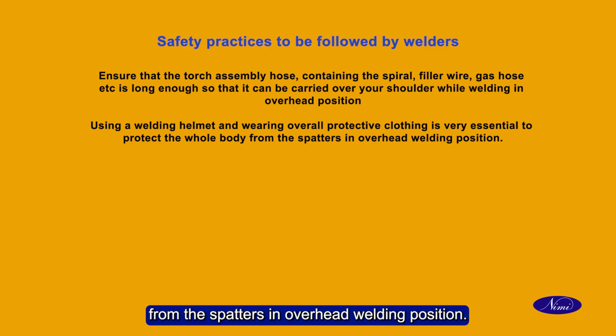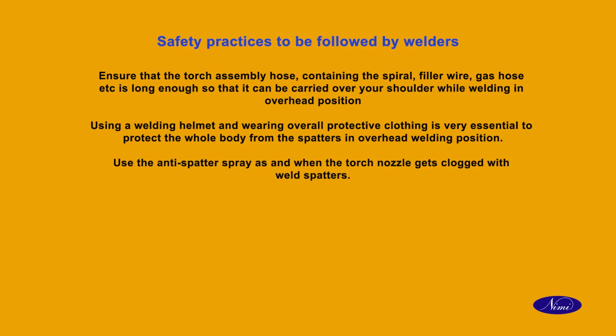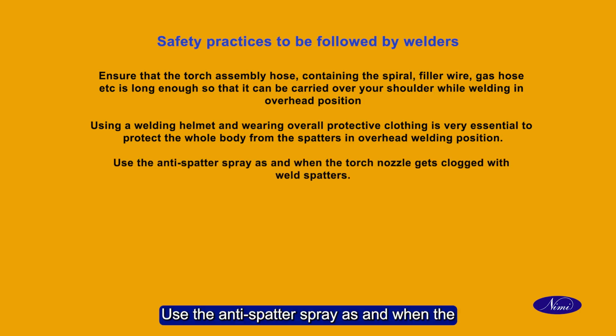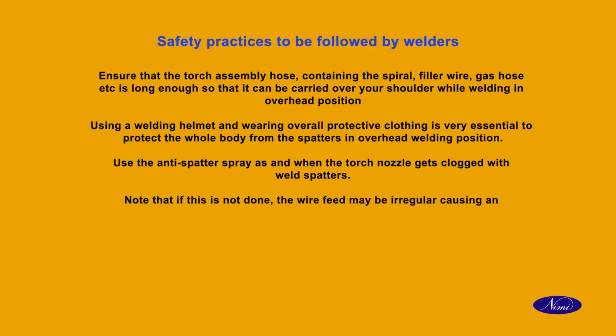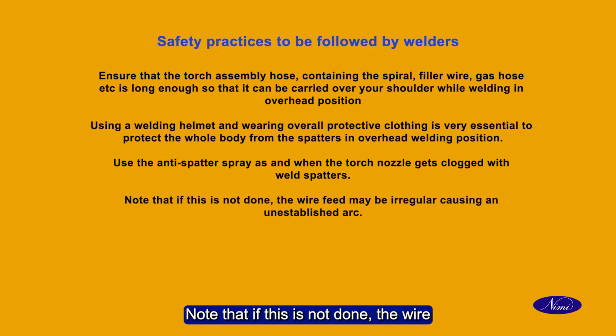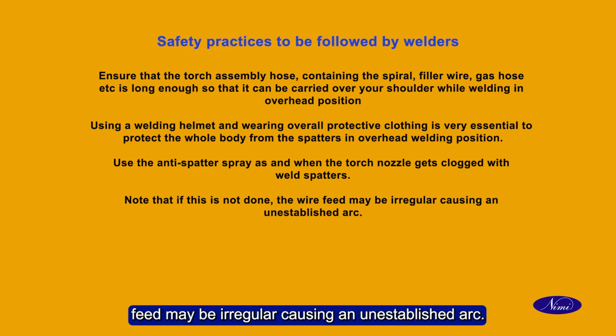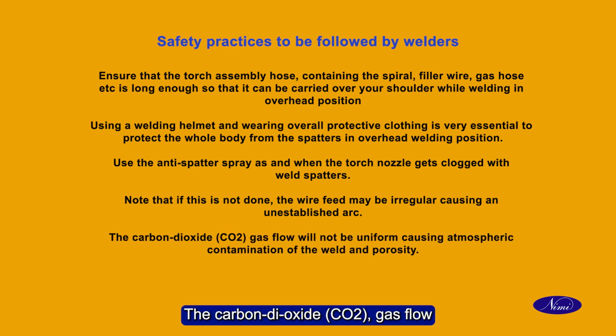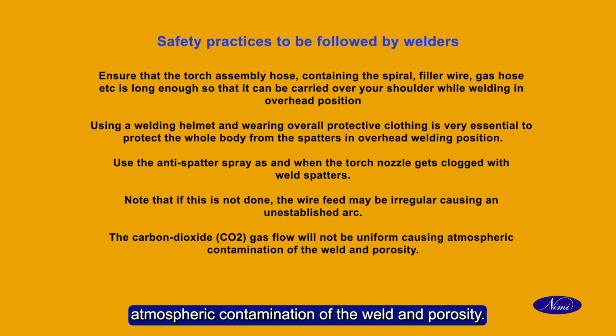in overhead welding position. Use the anti-spatter spray as and when the torch nozzle gets clogged with weld spatters. Note that if this is not done, the wire feed may be irregular, causing an unestablished arc. The carbon dioxide (CO2) gas flow will not be uniform, causing atmospheric contamination of the weld and porosity.